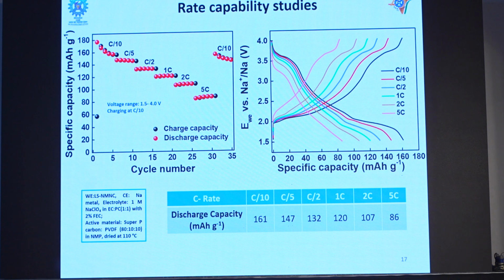So rate capability studies are done by charging or discharging the battery at different currents, because then we can see if your battery or your battery material has a potential to withstand different current rates. And this is the parameter which is translating to power density in a metal ion battery. Power density, again I said, determines the power of your battery. So this material has a much higher rate capability than its single parent compounds like P2, P3.